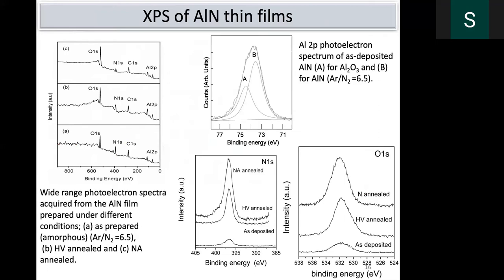Well, when you test that, we wanted to know whether an oxide phase exists after annealing or not. So what we did, we just tested by XPS. XPS will give you the bonding information between two elements, that is aluminum to oxygen, aluminum to nitrogen. This information you can get.